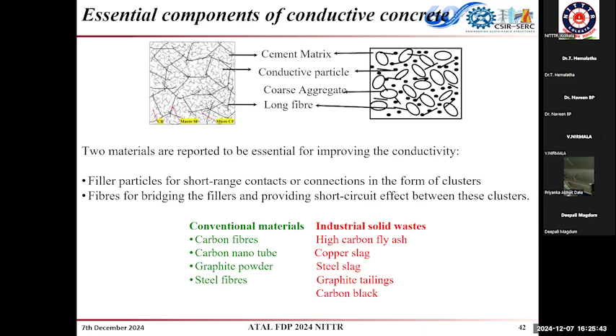So here in this case, our aim is to get conductivity. When high carbon content materials are available, because as I mentioned, in the conventional materials the carbon fibers and nanofibers provide conductivity, we have to see which byproducts have conductivity. So what we have done: this copper slag and steel slag have a good amount of Fe2O3 content. First we made some trials to see whether incorporating this slag improves the conductivity. So it was improving the conductivity.